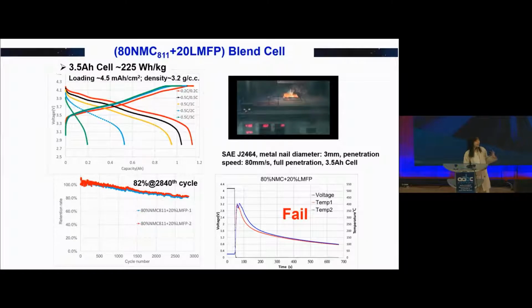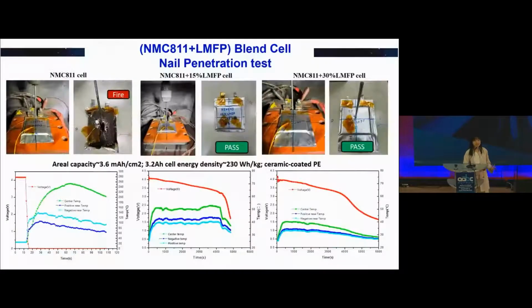So we were thinking to use a ceramic coated separator. With that, the NMC composite cells with 30% LMFP and 15% LMFP all passed the safety test by using the ceramic coated separator.